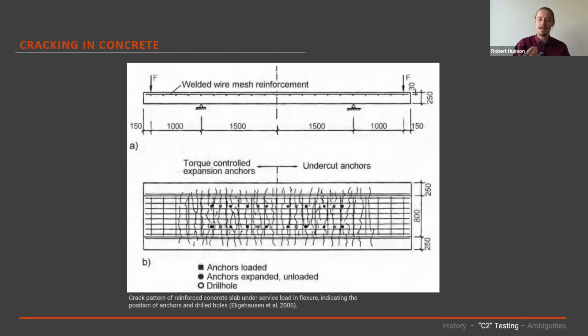But there is a baseline assumption when we talk about this: that when cracking occurs in concrete, the crack will occur where that anchor is. This wasn't just good judgment. It was based on a research program that was done in California in the 2000s. I've got a screenshot of one of the test results there. It was one of the test programs trying to build the data required to build these test programs for anchors. It looked at the probability that when we get cracking in concrete, that crack occurs where our post-installed anchors are. And the key takeaway is that it's very, very likely, much above random.